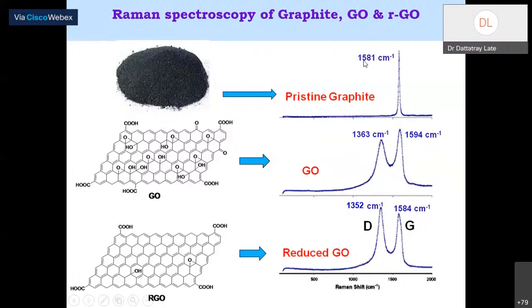You can see 1581 centimeter inverse to 1594 centimeter inverse, right? And in addition to that, we also have the 1363 centimeter inverse band, which is known as the D band. This band appears because you have converted your graphite into graphite oxide. When you have converted graphite into graphite oxide, we have a lot of functional groups. Defects have been added in the material, and this gives you this additional band or peak. Okay, now we have graphite oxide.